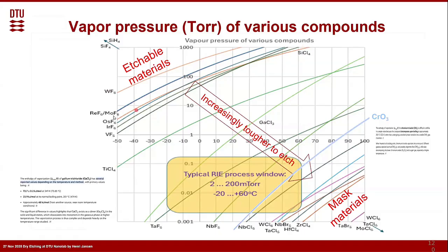And we can do that for any material or compound we are interested in. So that can be silicon, which is way up here. It means extremely volatile. And here, tungsten is still very good. And you go down and down. Here you have, let's say, titanium tetrachloride. And it's getting more and more difficult to vaporize, because the height of this one at a certain temperature is how fast the etch can go.